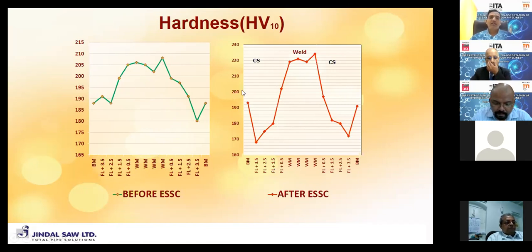This is increased because we have used the titanium boron wire, which has the tendency that if we reheat the titanium boron weld metal, it gets higher hardness. So other wires can be used if we want to reduce the hardness, but still this is well below the requirement of the standard.